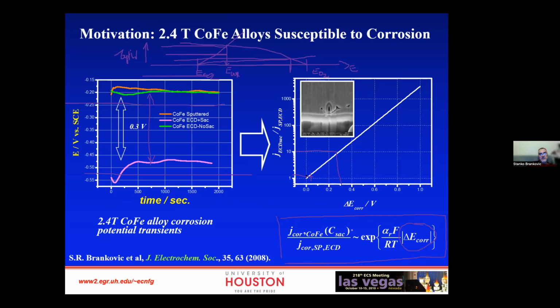And when I worked in Seagate, that was actually a huge problem because we had about 90% of the devices with cobalt iron failing after 3 months in humid weather. And since our production was in Thailand, where the humidity is about 100% most of the year, our products, which were ready to be shipped, had to be put in storage rooms.